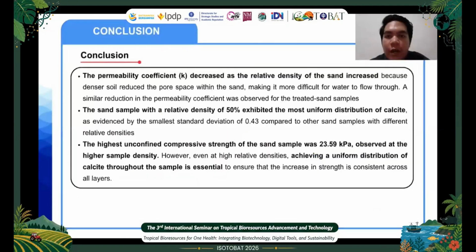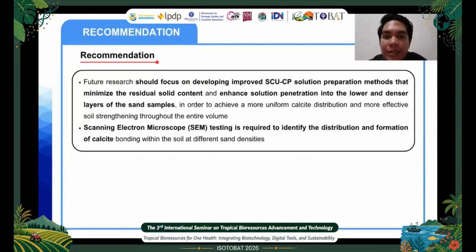Conclusions of the study are: the permeability coefficient decreased as the relative density of the sand increased. A similar reduction in the permeability coefficient was observed for the treated sand samples. The sand sample with a relative density of 50% exhibited the most uniform distribution of calcite. The high UCS value was obtained for the sample with the high density. The recommendations from the study are: future research should focus on developing an improved SCU-CP solution preparation method that minimizes the residual solid content, and scanning electron microscope testing is required to identify the distribution and formation of calcite bonding within the soil at different sand densities.